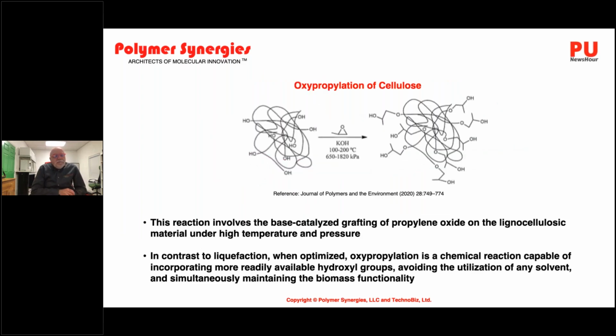There's another method of using cellulose to make polyols, and that's oxypropylation. In the presence of a catalyst and some caustic, the polypropylene oxide is grafted onto the lignocellulosic material under high temperature and pressure. In contrast to liquefaction, when optimized, this oxypropylation is a chemical reaction capable of incorporating more readily available hydroxyl groups. So it avoids the solvent, and it's a grafting process, and it's another way of functionalizing biomass to make polyols.